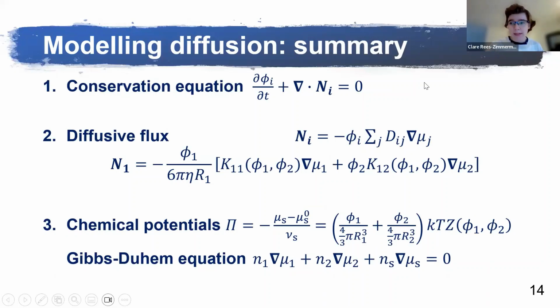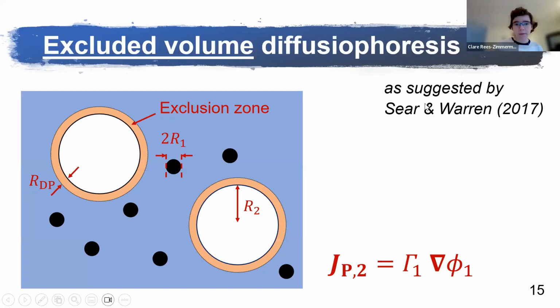So this slide summarizes the equations from the previous 3 slides, which I'll put together to form some PDEs to describe the diffusion process. I put together the conservation equation, the diffusive flux, chemical potentials, and the Gibbs-Duhem equation to derive equations that should be valid for concentrated dispersions. I also include in this model a certain type of diffusiophoresis, which is called excluded volume diffusiophoresis. That's because it was hypothesized that it may be what's causing the accumulation of small particles at the top surface. I wanted to test this.